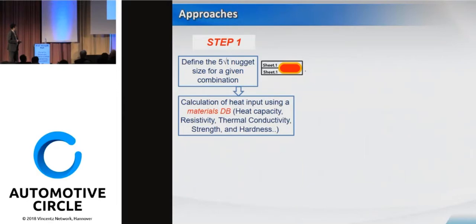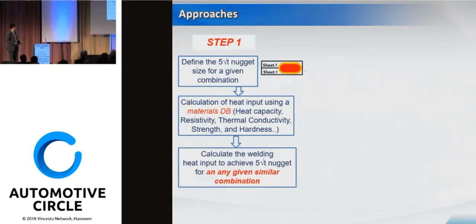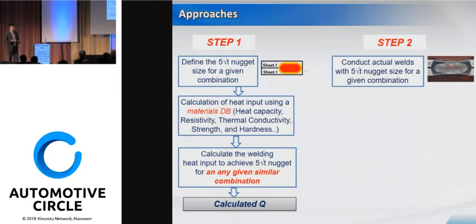And then I calculate the heat input using the material database. I use the heat capacity, resistivity, thermal conductivity, strength, and hardness, and so on. I use about 9 or 10 material databases. And then I calculate the welding heat input to achieve the 5√t nugget diameter for any given similar combination here. So I got a calculated total heat input in here. And move on to step 2.